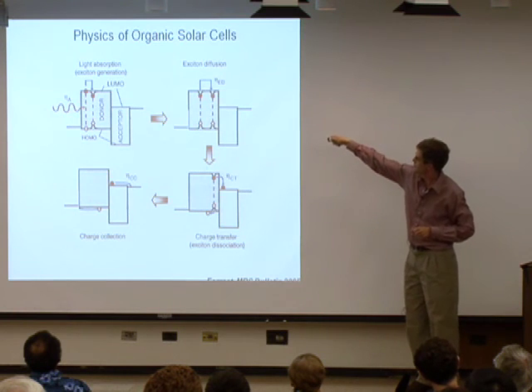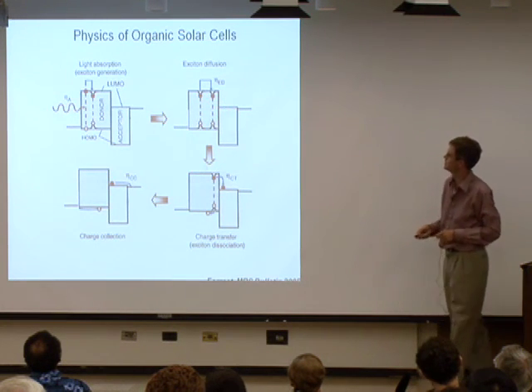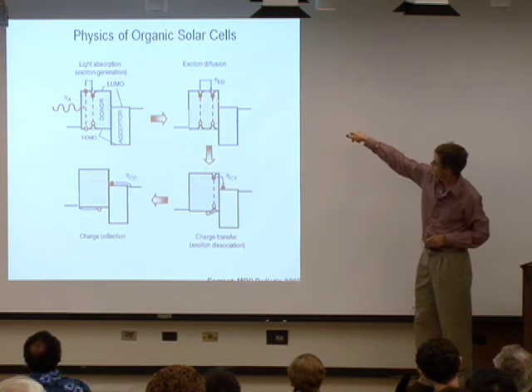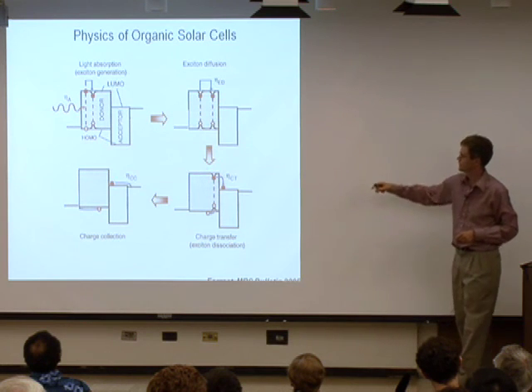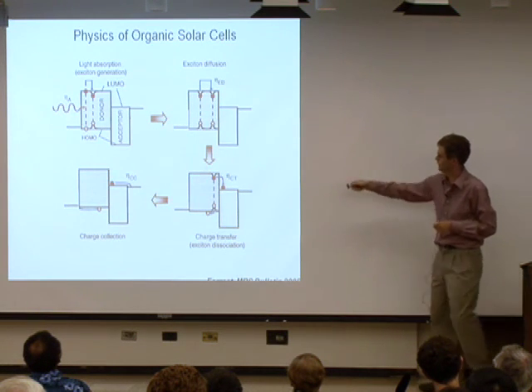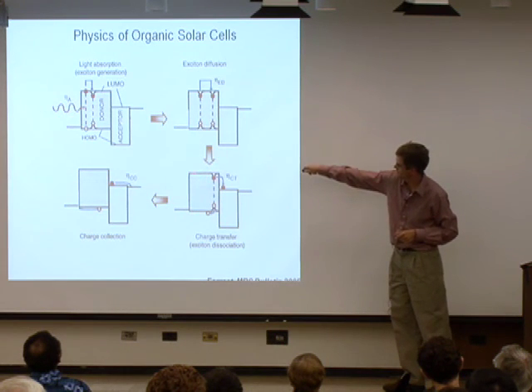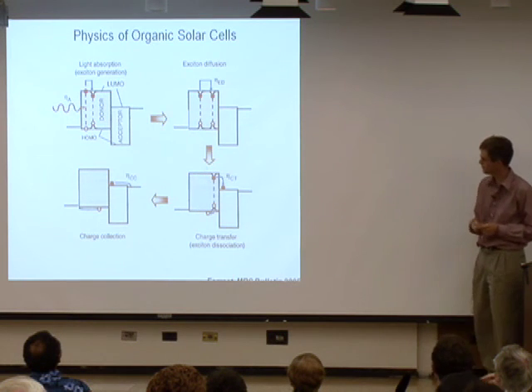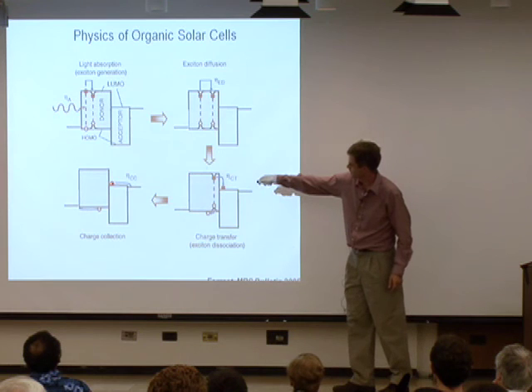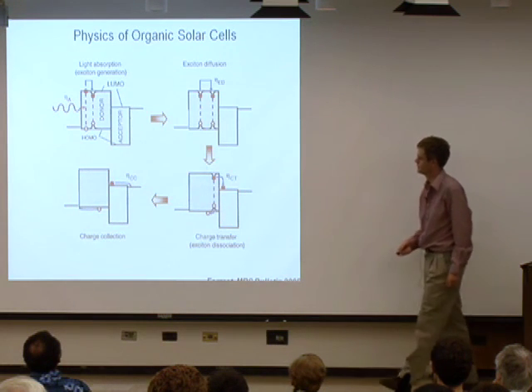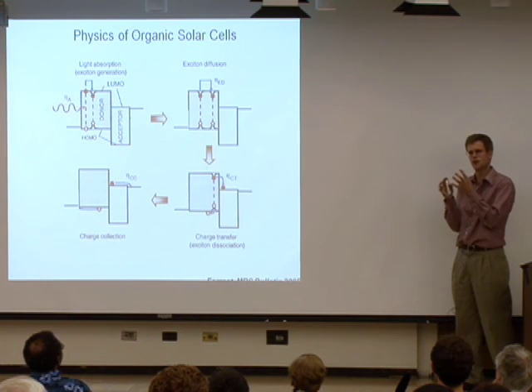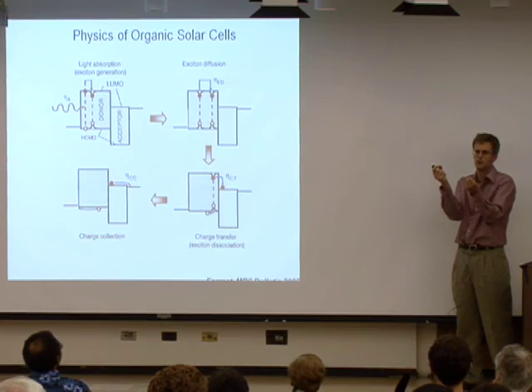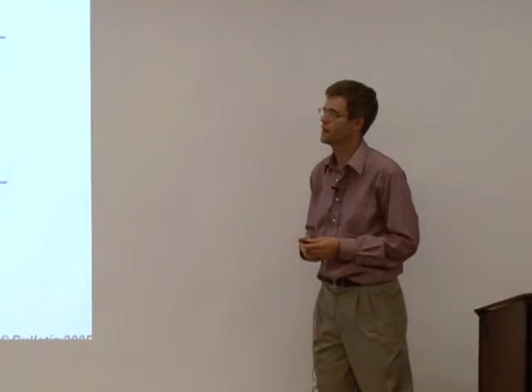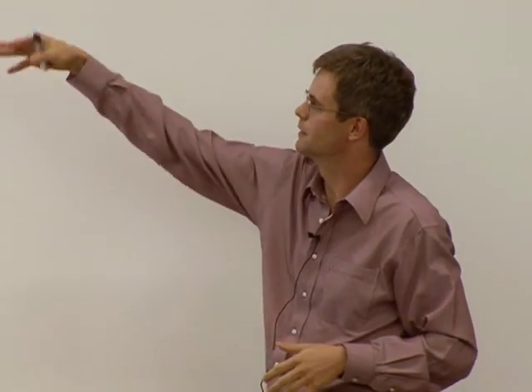So what happens is the exciton diffuses to an interface between two semiconductors that have offset energy levels. And when it gets there, the electron can transfer over to the semiconductor with the lower lying conduction band. And I should add that these are the band gaps. So the top is the conduction band, and the bottom is the valence band. And then after that happens, the electron can come out to one electrode, and the hole can come out to the other. So we've essentially used two semiconductors to help separate the electron and hole. And it's interesting to note that this is exactly what happens in photosynthesis. After light is absorbed, to keep the electron from rapidly falling back down, it undergoes electron transfer to a different part of the photosynthetic complex.